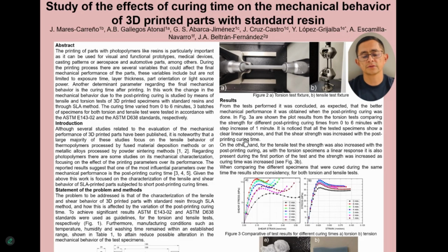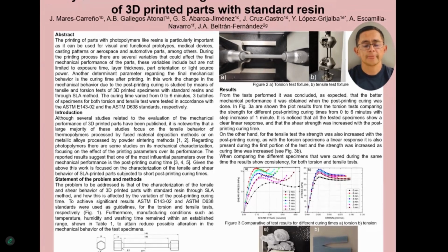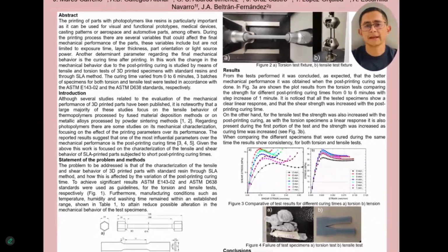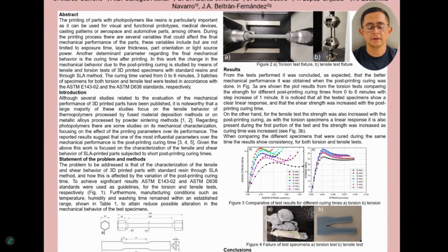Although several studies related to the evaluation of the mechanical performance of printed parts have been published, it's noteworthy that a large majority of these studies focus on the tensile behavior of thermopolymers processed by fused material deposition methods or on metallic alloys processed by powder sintering methods. Regarding photopolymers, there are some studies on mechanical characterization focusing on the effect of the printing parameters on its performance. The reported results suggest that one of the most influential parameters of the mechanical performance is the post-printing curing time.